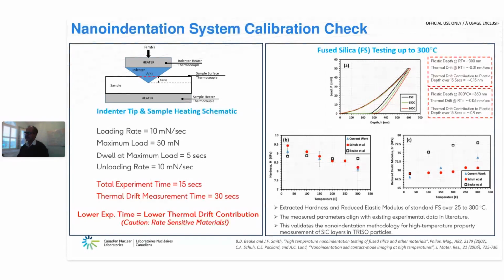So using these load displacement curves at different temperatures, we extracted hardness and reduced elastic modulus for the standard fused silica from room temperature to 300 degrees C. And you can see the hardness versus temperature. Our data is in blue triangles: room temperature, 150, 300 degrees C. So the hardness did decrease with increasing temperature, and it